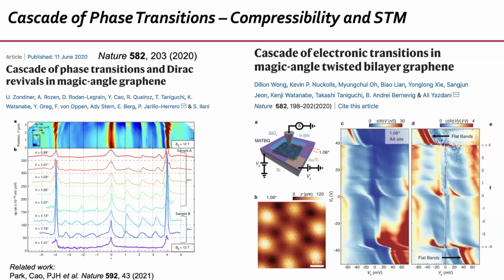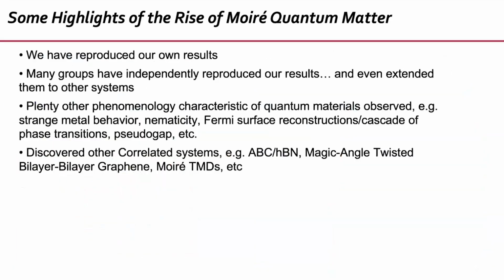Okay, in 2020, both in a collaboration between Shahal Ilani and my group, and also in work with Ali Yazdani, STM work, we saw that at these integers of 1, 2, 3 electrons or holes per moiré unit cell, you actually have a phase transition at each of them. So there is a cascade of phase transitions, indicating Fermi surface reconstructions and also polarization of your electronic system. You go from having spin and valley degeneracy to having only one of them or the other, or combinations. That was measured in the inverse compressibility, these bumps at each integer. Those are the cascade of phase transitions, and you can see them also in STM very nicely. As you can see, two papers at the same time were published back to back, and that's going to happen in all the highlights that I'm going to mention.